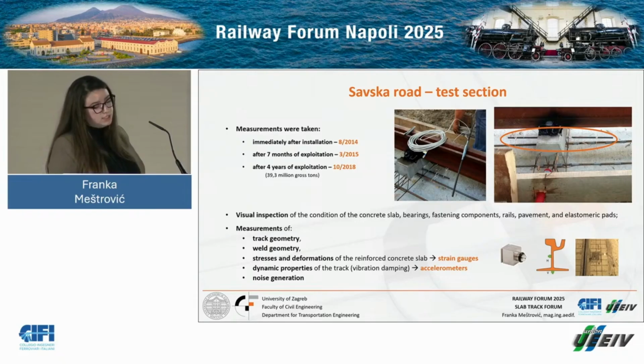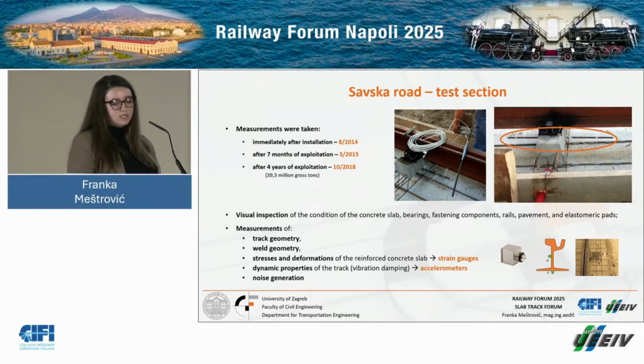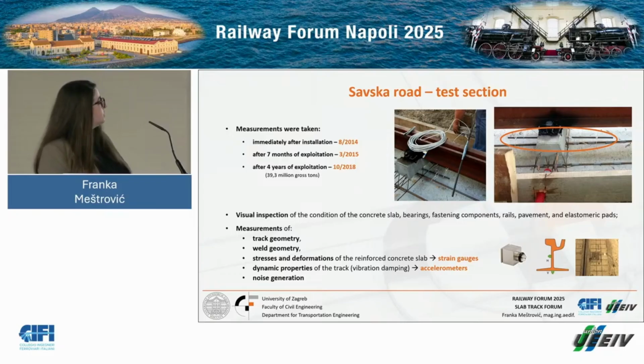Furthermore, it was, like I mentioned, measured, so certain measures were taken immediately after installation. That was 2014, then 7 months after exploitation in 2015, and after 4 years of exploitation in 2018. By that time, almost 40 million gross tons had passed over the system. Apart from visual inspection of the concrete slab and the bearings, fastening elements, rails, pavement, and elastomeric pads, some other measurements were taken. So my colleagues measured track geometry, weld geometry, stresses and deformations of the concrete slab.